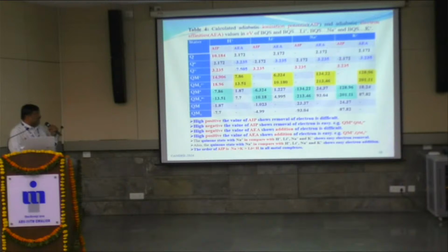But if we calculate the adiabatic ionization potential values and adiabatic electron affinity values for various states of the benzoquinones, the higher positive values of ionization potential show that removal of an electron is difficult. Higher positive values of this AIP in these various oxidation states of quinone mean removal of an electron is difficult, but negative values of the adiabatic ionization potential show that removal of an electron is easy for quinone metal radical cations. And if we compare the adiabatic electron affinity values, high negative values of electron affinity show that addition of an electron is difficult, and high positive values show that addition of an electron is easy.